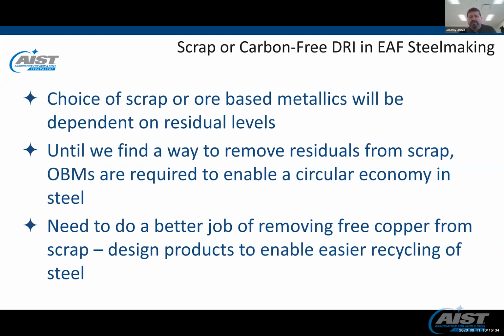We also need to do a better job of designing products to remove things like free copper from the scrap. Because, for instance, if you remove all of the free copper from an end-of-life vehicle, you can probably produce a shredded scrap with about 10 points of copper. In reality, we see shredded scrap with copper levels ranging from 15 points to as high as 35 points. So obviously, in some cases, we're doing a very poor job of removing the free copper. And the free copper is that copper that's not tied up directly in the steel, but is in other components in the material that we're processing.